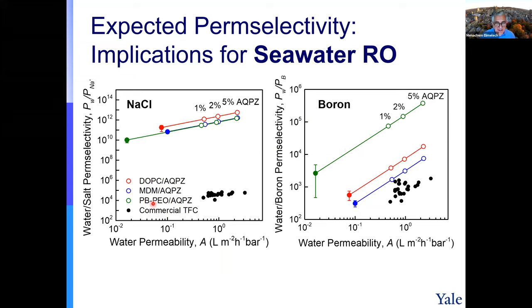But let's take the best polymer, the PB here. This is the current, again, this is the water boron perm selectivity. The rejection goes in this direction. This is the water permeability of the membrane. This is the current membranes.